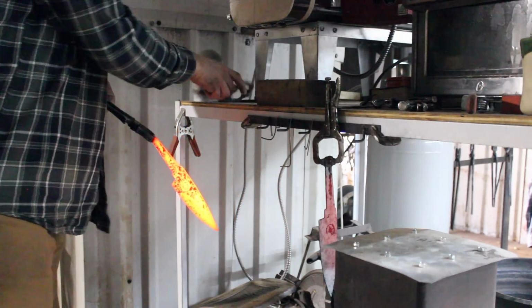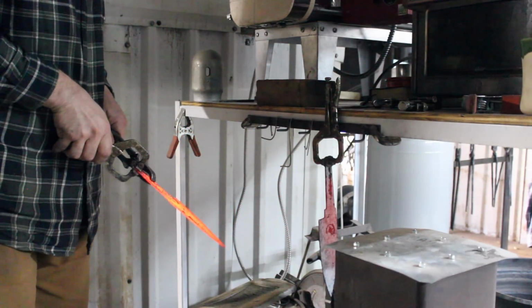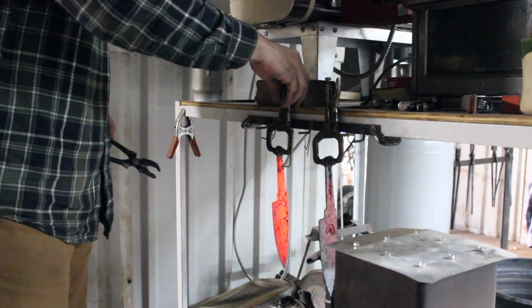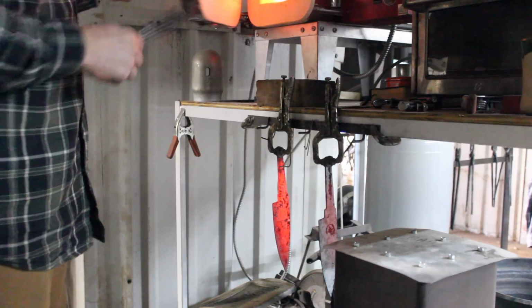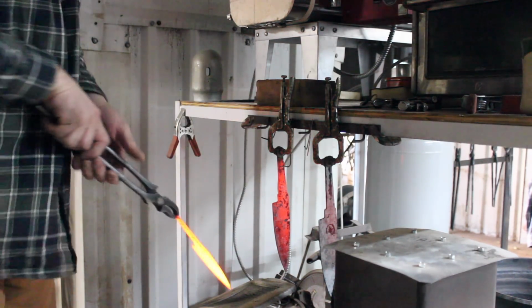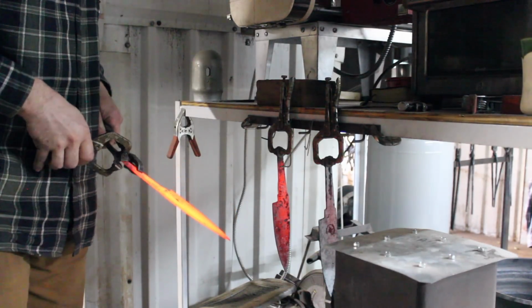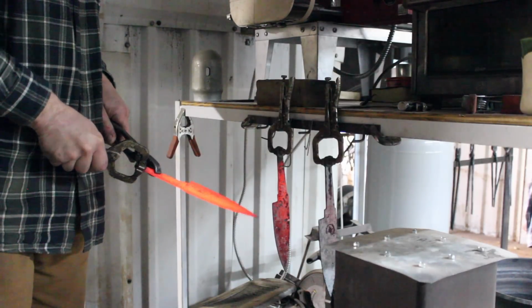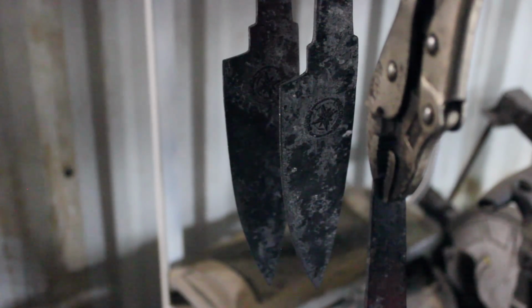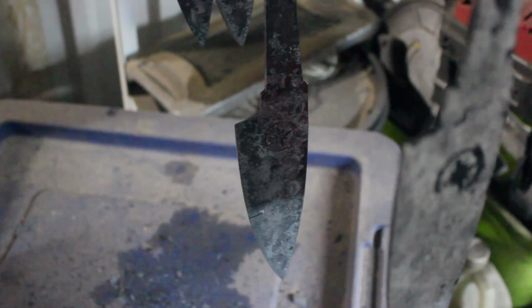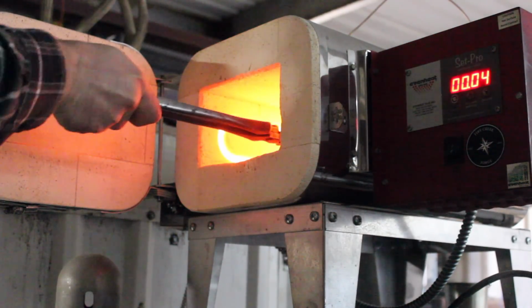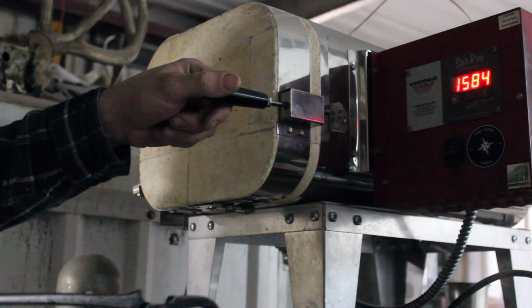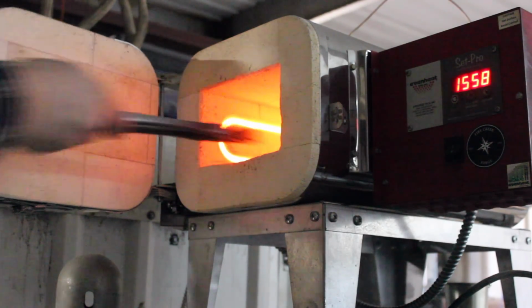This first step here is called normalizing, and normalizing is where you heat the steel to a specific temperature, usually between 1600 and 1650 degrees. And this is designed to create a uniform grain structure and to relieve the stress created through the forging process. During this process, once the blades cool down to a black heat, there's no incandescent color showing, we can go ahead and put them back in the kiln and repeat the process several more times at specific temperatures.